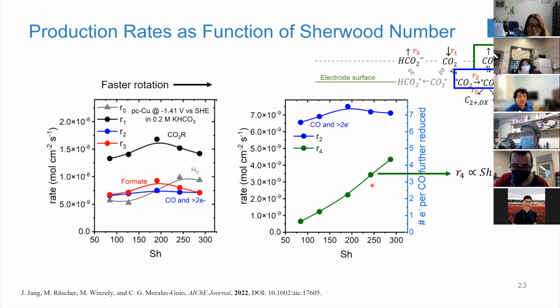And also many times when you add gold or silver, what you're doing is just changing one parameter. You're not changing intrinsically the activity of copper, but maybe you increase that CO concentration at lower potentials, because now you have something that is better at making CO. And then that CO concentration at earlier overpotentials changes your selectivity. But what we see now is that we can describe that again with the same intrinsic kinetics of copper, understanding that you have something that produces more CO perhaps. Okay, yeah, thank you.